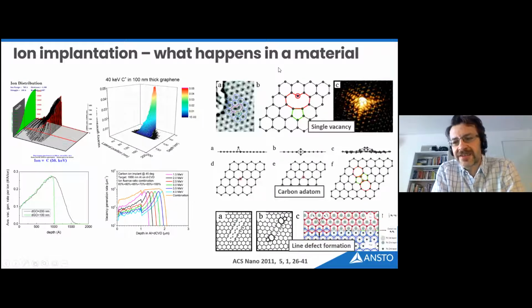The very precise depth at which ions are implanted, and the rate at which they produce displacements, is one of the best characteristics of ion beams used for material modification. On the right side, what you can see is, for example, when we irradiate 2D materials like graphene, we can create point defects, single vacancies. Also, we can create double vacancies. Also, we can create an additional carbon atom added to a layer, or we can produce complex defects like line defects or dislocations.